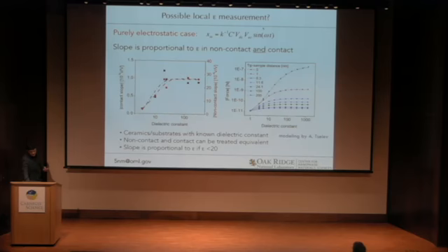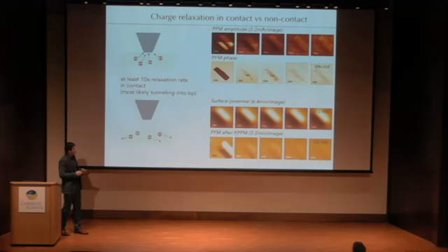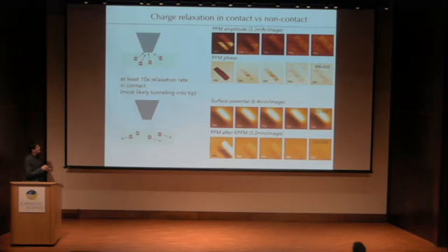So finally, we can look at the charge relaxation rate, and here too we find something that could be expected, but it is very nice to sort of confirm that the charge relaxation rate from the material when the electrode is present, so in a scale capacitor, is far larger than the charge relaxation rate when the capacitor is taken out. And so the way we explain this property is that if you think about the charge distribution that we create with the probe in the material, it will be localized pretty close to the surface.